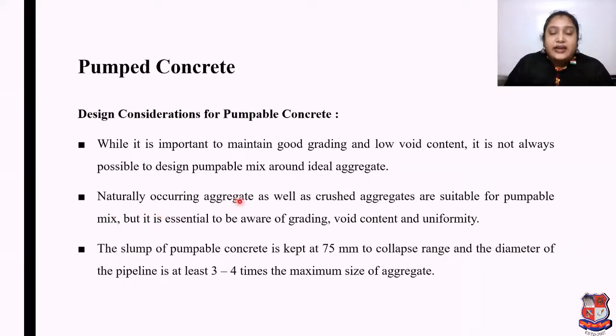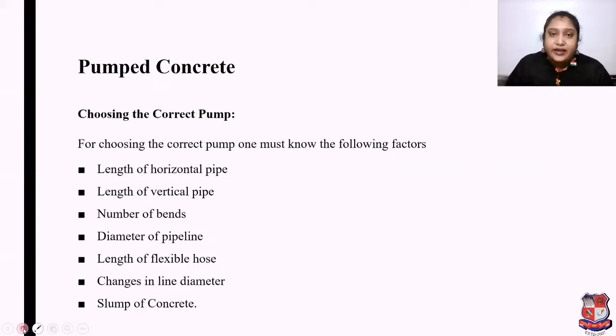Naturally occurring aggregate as well as crushed aggregate are suitable for pumpable mix, but it is essential to be aware of grading, void content and uniformity when preparing that concrete. The slump of pumpable concrete is kept at 75 mm to collapse range, and the diameter of the pipeline is at least 3 to 4 times the maximum size of aggregate.